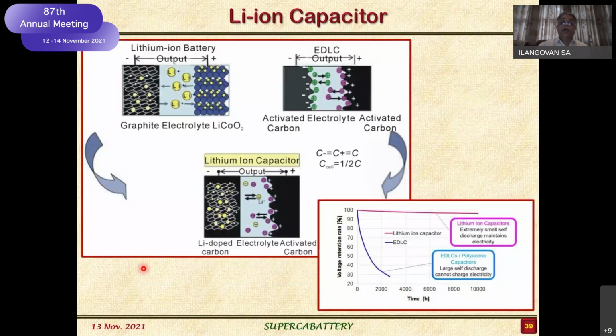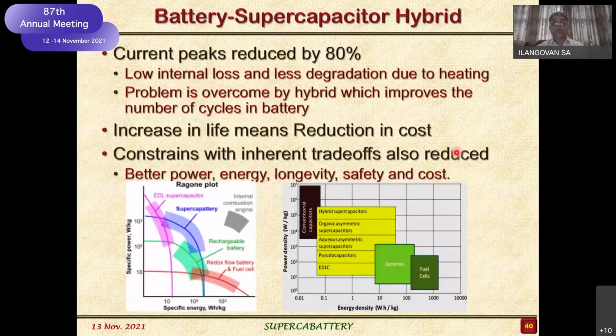So this is how we did the combination of battery anode and cathode. Here also anode and cathode of the supercapacitor. If I can combine these two, if I replace the cathode by the cathode of the electrochemical double layer capacitance, we are able to get a better voltage as well as self-discharge aspect. But still, one of the electrodes does not have enough energy. This is where the problem is. I am able to increase the energy, I am able to increase the power, but energy is still not fully utilized from the battery side. So this again becomes a problem. So what should we do? That is where we were trying to improve.